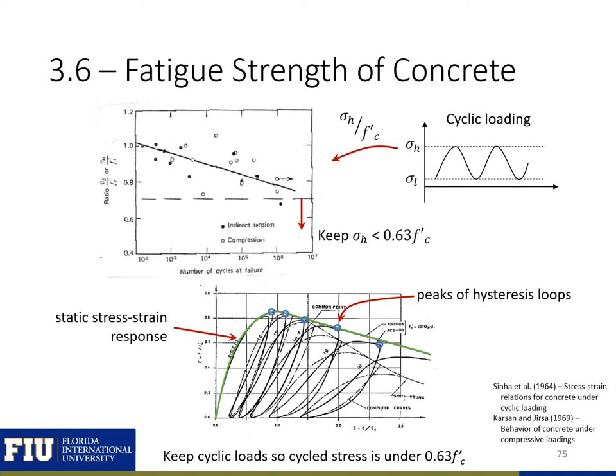This slide shows two plots describing the fatigue strength of concrete. The top plot shows fatigue testing on a number of different samples with a total number of cycles required to cause failure at different stress levels. Lower levels of cycle stress result in more cycles required to cause failure. Karsan and Jirsa recommend keeping the cycled stress on concrete under 0.63 f'c. Note that the only stress limit that takes into account fatigue in ACI is for Class U and T prestressed members, where the concrete compressive stress under prestress and total load must be under 0.6 f'c.